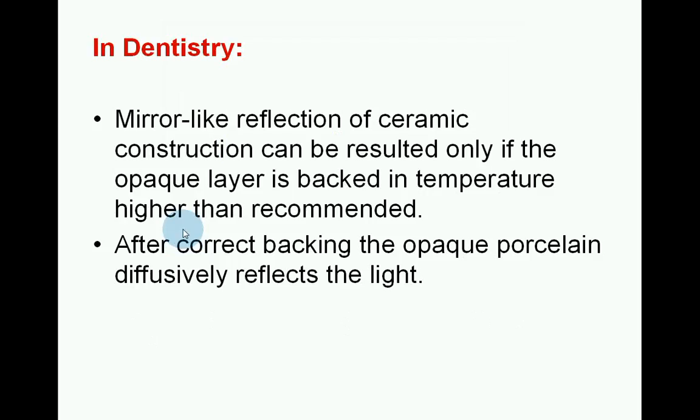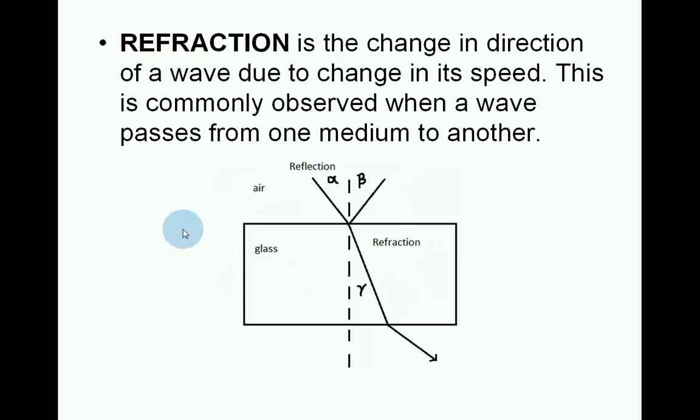In dentistry, mirror-like reflection of ceramic construction can result only if the opaque layer is baked at a temperature higher than recommended. After correct baking, the opaque porcelain diffusively reflects the light. Refraction is the change in direction of a wave due to a change in its speed, commonly observed when a wave passes from one medium to another.